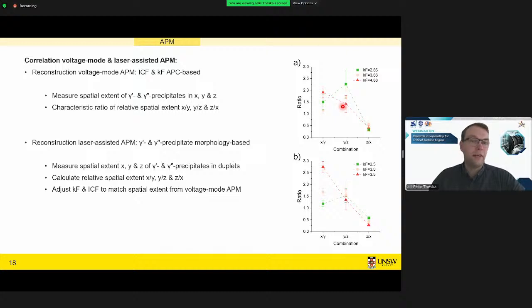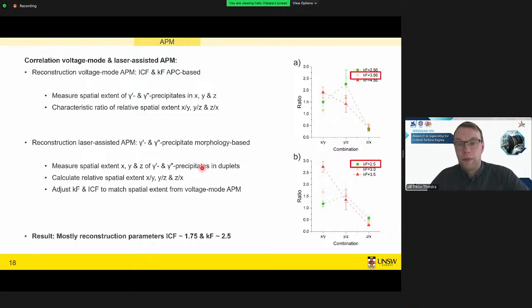Now we can take our laser-assisted data and do the same. We play around with the reconstruction parameters until our relative particle shape fits that of the voltage mode. In this case, I put some red boxes here for the appropriate reconstruction parameters, and you see these relative sizes of the particles are very similar to each other.